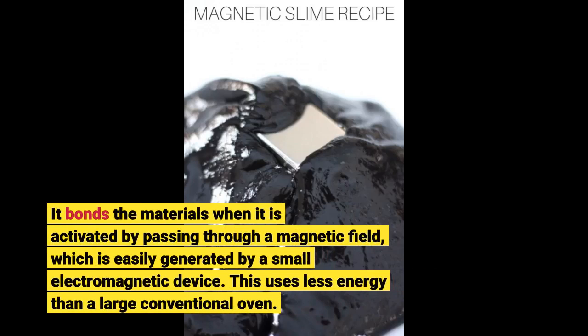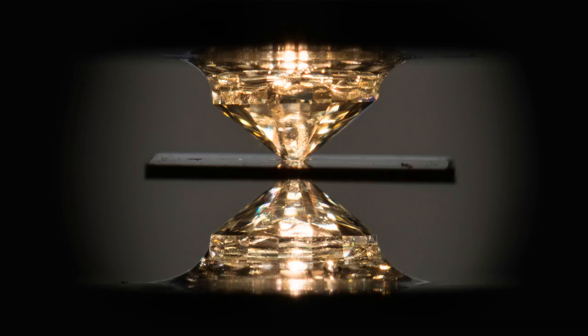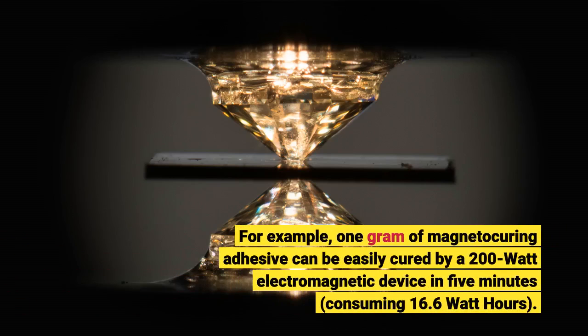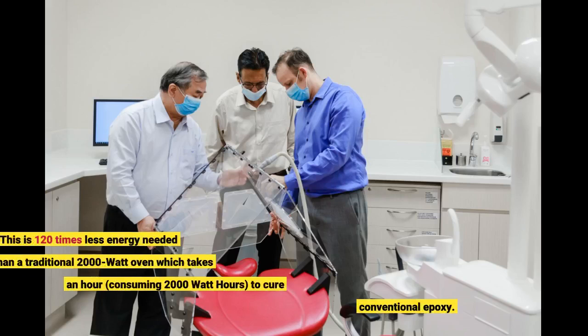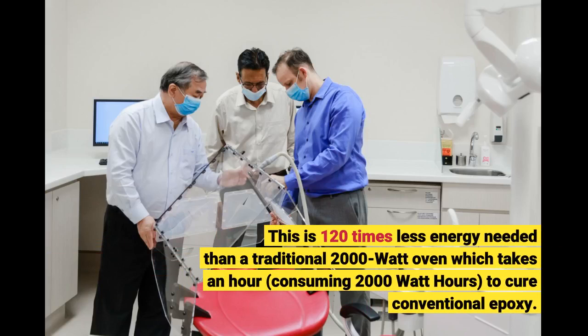It bonds the materials when it is activated by passing through a magnetic field, which is easily generated by a small electromagnetic device. This uses less energy than a large conventional oven. For example, 1 gram of magnetocuring adhesive can be easily cured by a 200-watt electromagnetic device in 5 minutes, consuming 16.6 watt-hours. This is 120 times less energy than a traditional 2000-watt oven, which takes an hour, consuming 2000 watt-hours, to cure conventional epoxy.